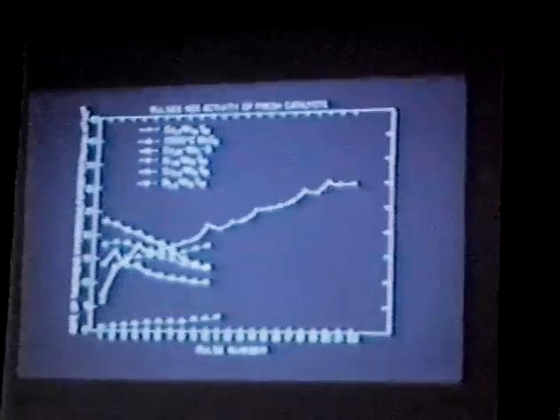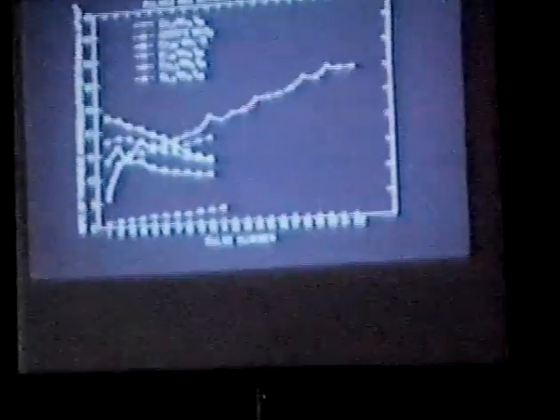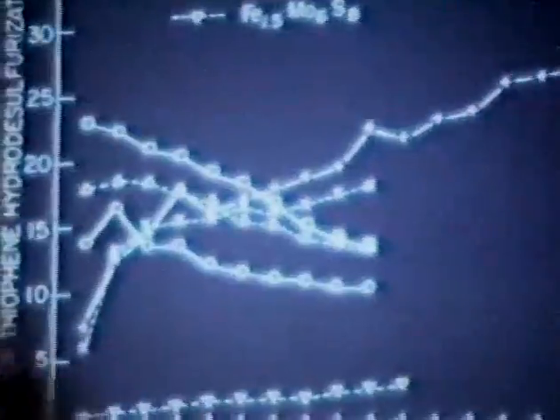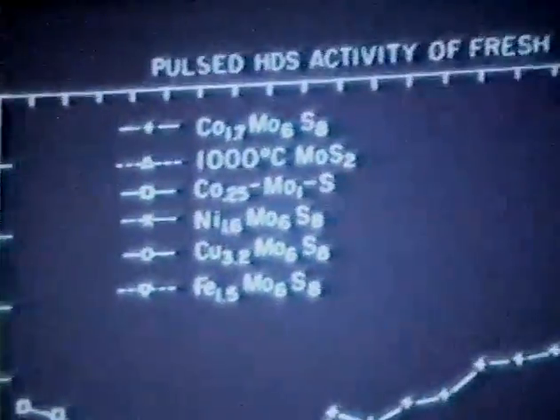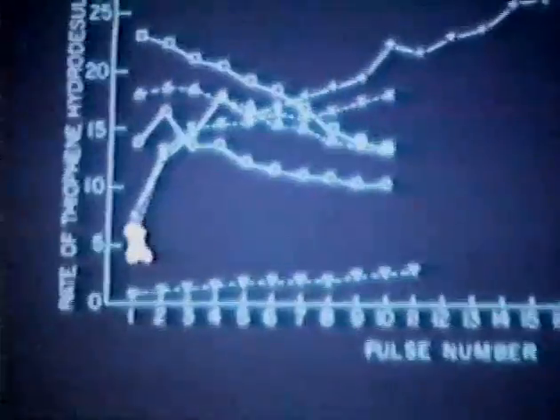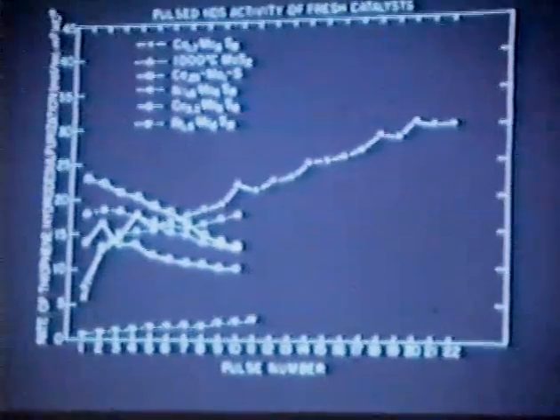Well, we've been quite interested over the years to try to sort out what the reasons for this activity are, and to try to examine the stability of the catalyst. And without going into great detail here, there are some compounds for which there does seem to be a kind of promotional effect. Here, where we've looked at consecutive pulses of thiophene going over the catalyst, some of the catalysts do show some gradual deactivation, but there are some phases, for example, the cobalt Chevrel phase compound, that does undergo some type of activation.